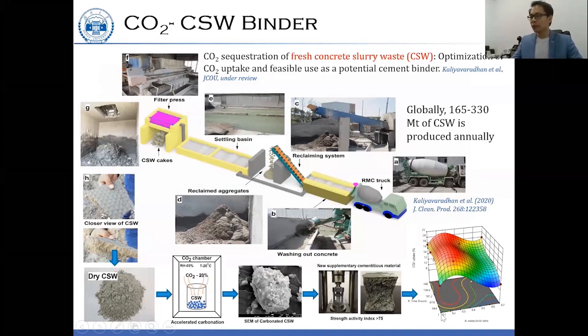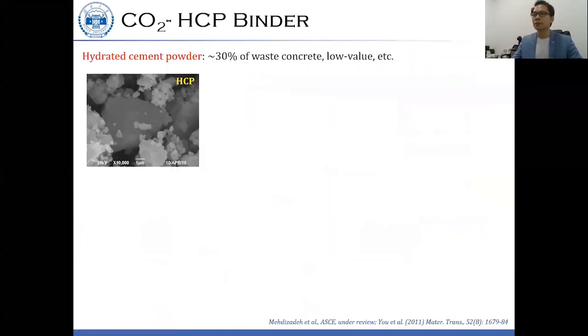We carried out tests for the maximum CO2 uptake by this material, and we found a maximum of 20% CO2 uptake at a water to solid ratio of around 0.25 at 72 hours of reaction. Based on the strength activity index, this material could be used as a new supplementary cementitious material in cement and concrete.